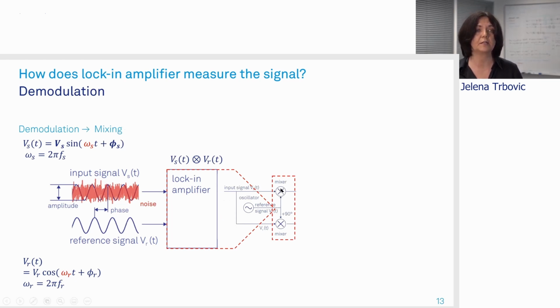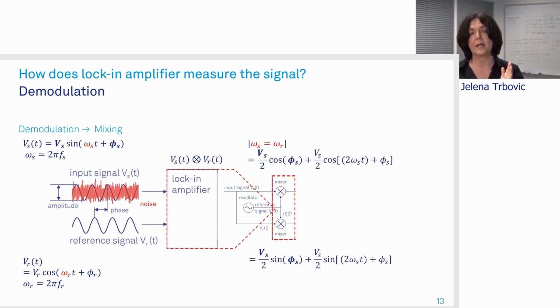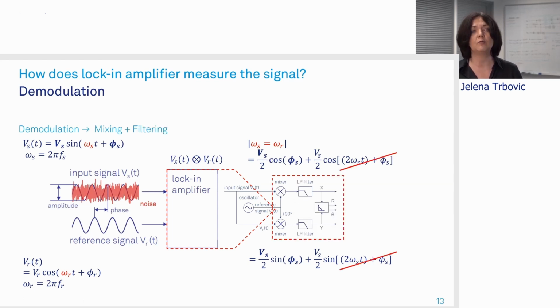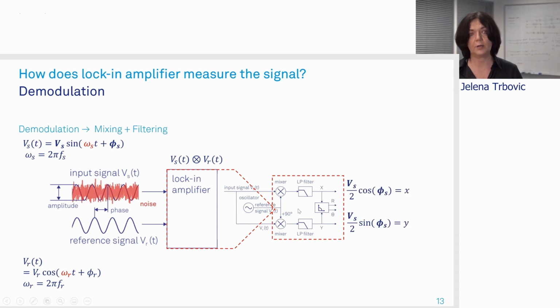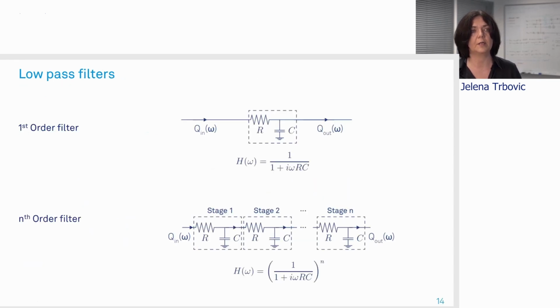And then it projects these results in and out of phase of the reference frequency. And then when we're exactly at the reference frequency, we have two terms in this product. We have this DC term that has amplitude and the phase in both parts, and we also have this time varying part, which is proportional to 2 omega, or two measurement frequencies. And this is something we want to get rid of, and we do this by using low pass filters, and we are then left only with the X and Y components of these signals from which we can construct the amplitude and phase. And this is how the lock-in works in a nutshell.